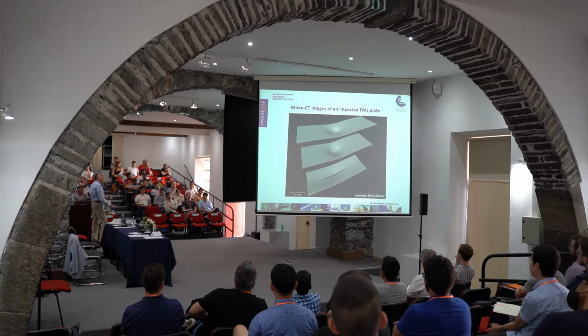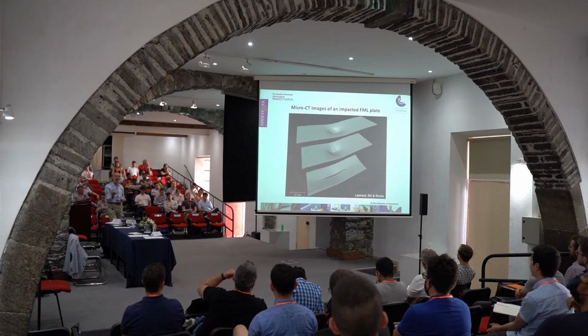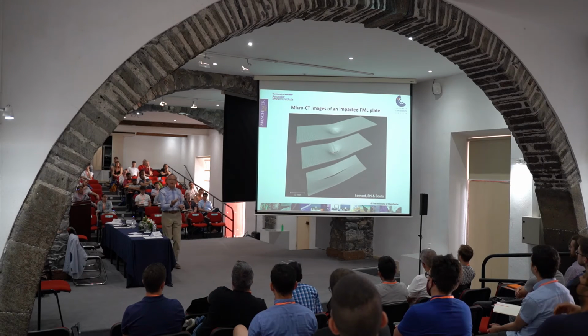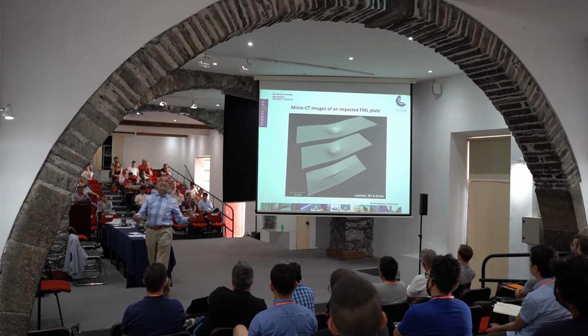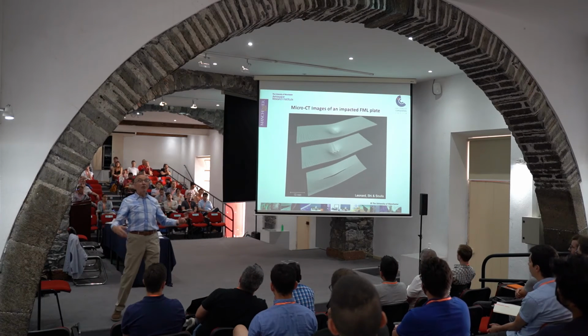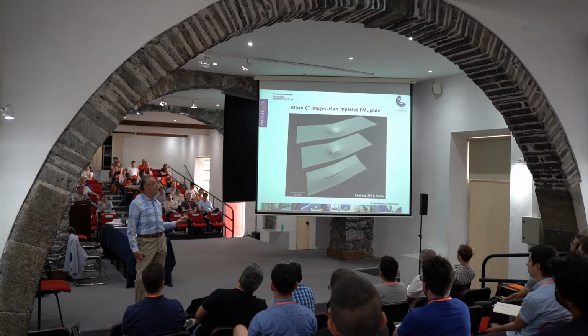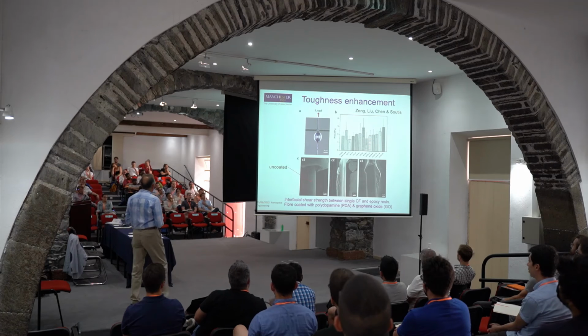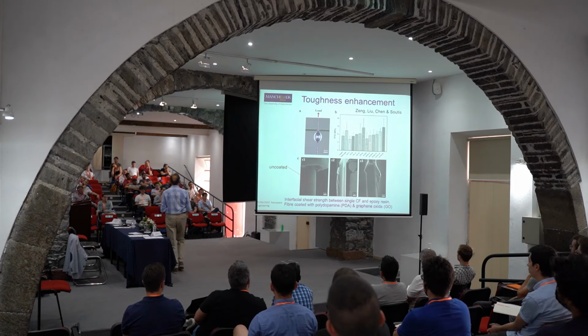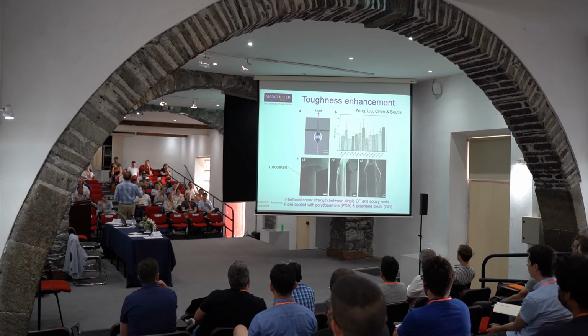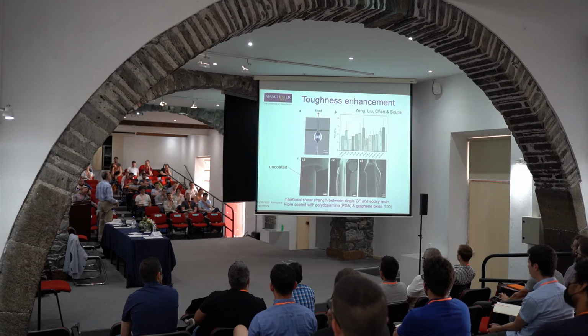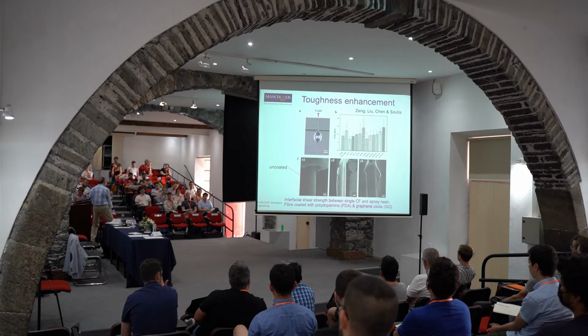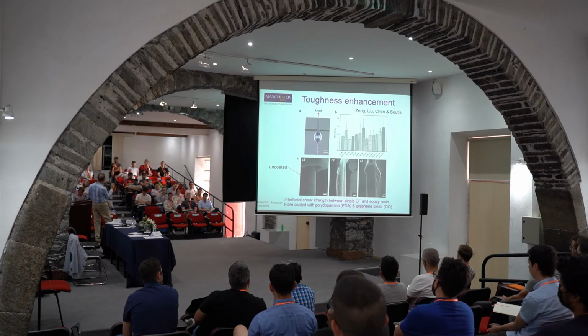And here's a carbon fiber metal laminate we have tested in our lab, where we can see that the composite splits. The aluminum undergoes extensive plastic deformation, but overall you don't get perforation. And that's another way of increasing toughness and making your composite tougher. Because you remember, we said that composites are material systems, and you design them for a specific need that you are facing. And here another way of improving toughness is to go back to the design of the fiber matrix interface.